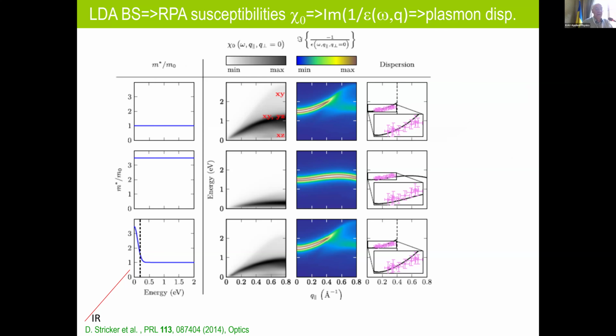And we see that for the effective mass of 1, we get good agreement, or for an effective mass which is high at low energy but decreases to 1 at high energy, we get good agreement. But when we take for the whole energy range an effective mass of 4, which is measured by ARPES, then we have less agreement.